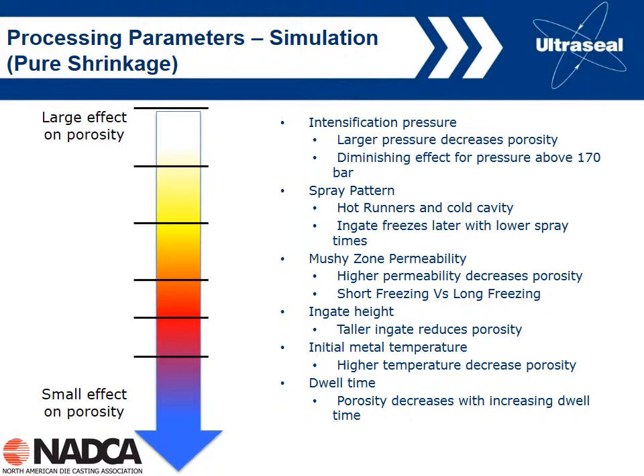Second here, we're talking about spray. So what we're saying is that spray can have the second largest effect, and with spray we can locally control the die temperature, we can create cold spots on the die, we can change the distribution of the die, and we can control, therefore, where the porosity ends up. Hot areas of the die tend to attract porosity, colder spots tend to push porosity away.